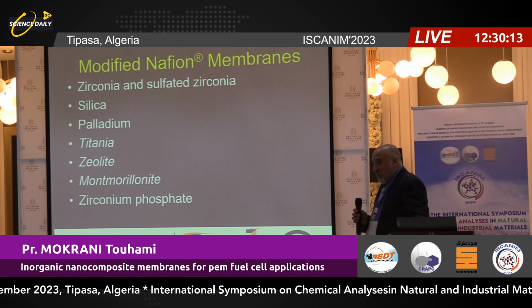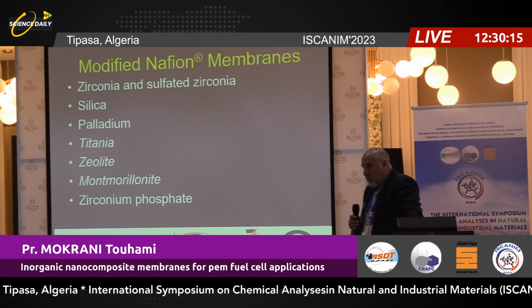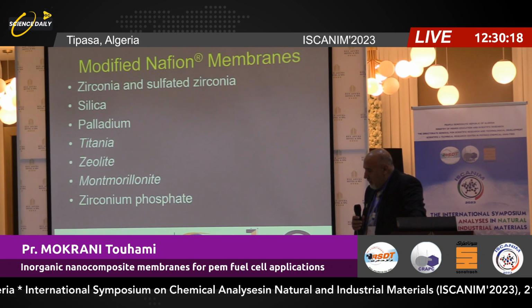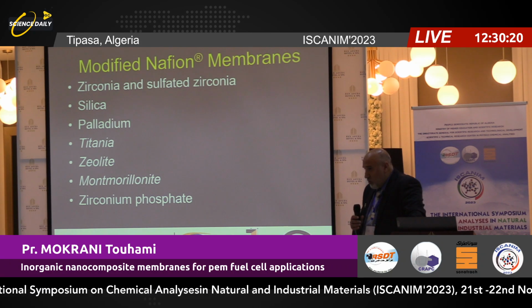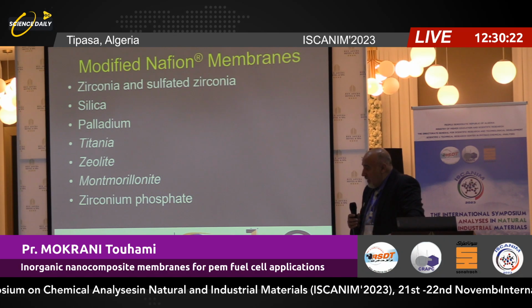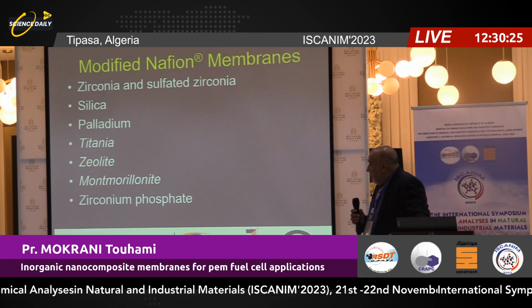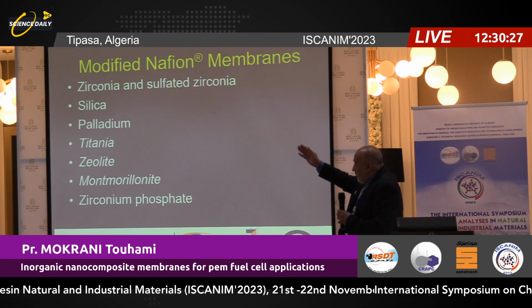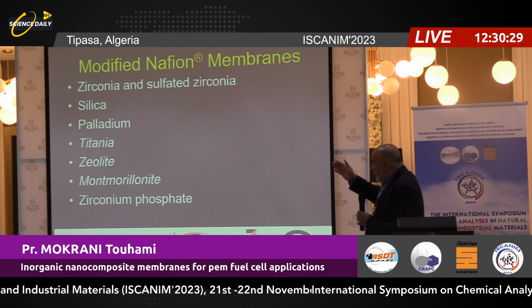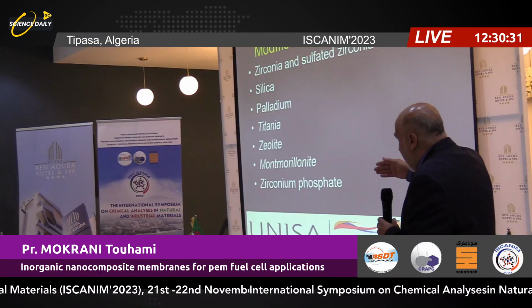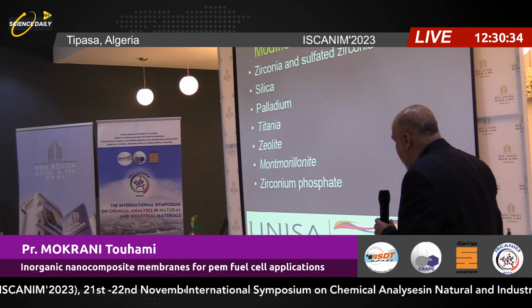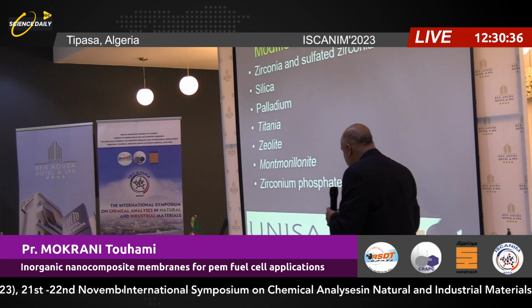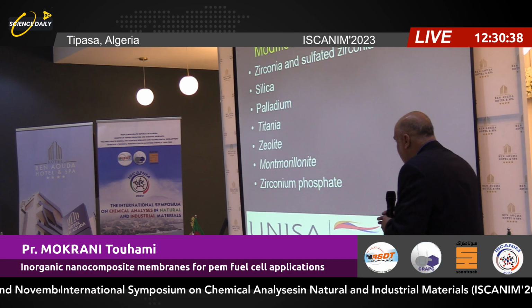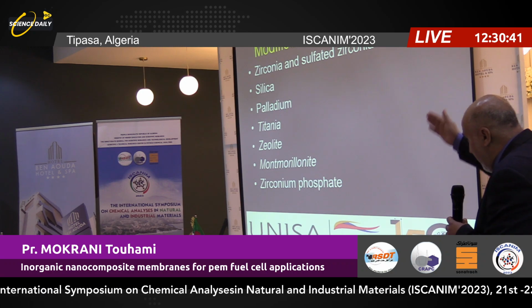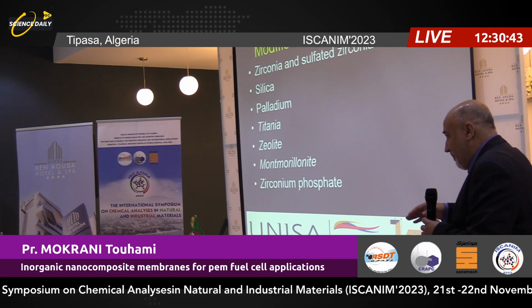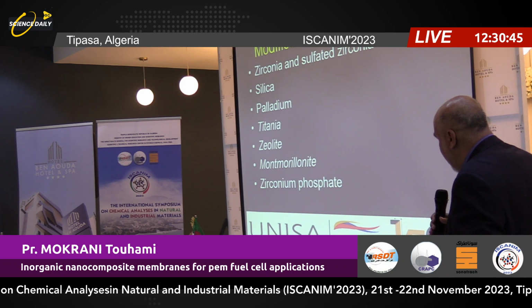So how can we cover some of the disadvantages of Nafion? The most important one is to add inorganic materials. Like in this case, we use zirconia, sulfated zirconia, silica, palladium, titanium, zeolite, clay, and zirconium phosphate. In our experience, the best one is zirconium phosphate, which I am going to speak about later.